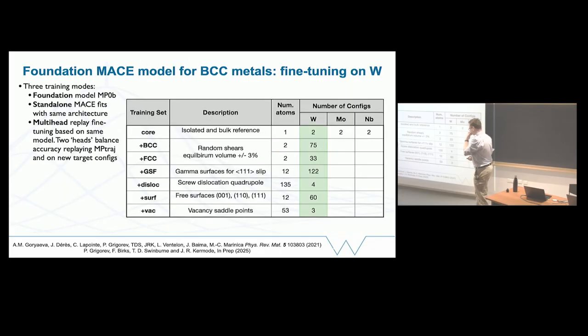I wanted to do it quite cheaply, so we just took a couple of hundred DFT configurations for tungsten. And then I was interested in seeing, if I try and fix the behavior for tungsten, can I also improve the extrapolation to other metals? I did this by only including a tiny, tiny amount of data for the 2 other metals, just to set the zero for the energy, basically. I put in 1 atom on its own and 1 bulk crystal for the other 2 metals, and a couple of hundred configurations covering the sorts of things I would like to do.